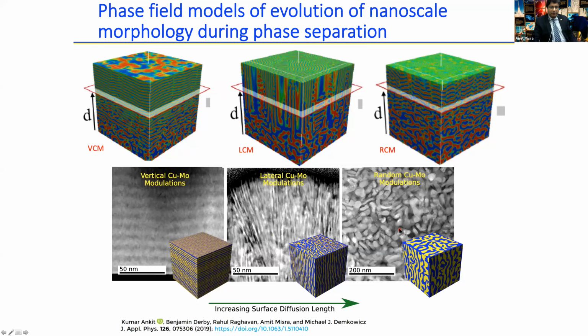And this is simply a competition between the rate of mixing, which is determined by the deposition rate, and the rate of demixing, which is determined by the interdiffusion. So at elevated temperatures, depending on the two elements, one element diffuses faster than the other. And so you'll see different kinds of patterns that evolve. All of these are nanoscale, and the shape changes. And the question would be, how do the properties change?